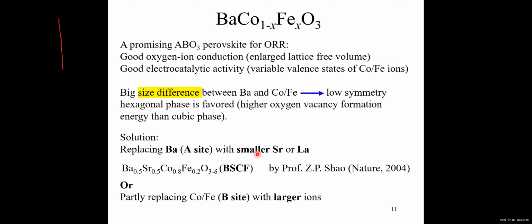However, on the A site is Ba and the B site is cobalt or iron. Because the A site and B site size difference is quite large, this will cause low symmetry, and this will favor the hexagonal phase. So the cubic phase will not be favored due to the large size difference between A site and B site.